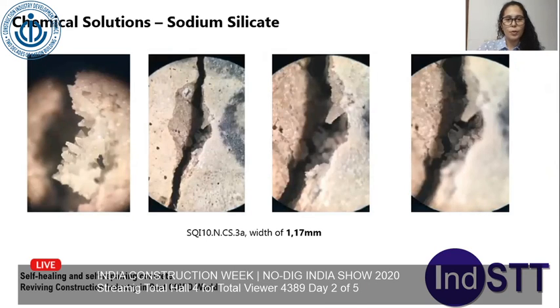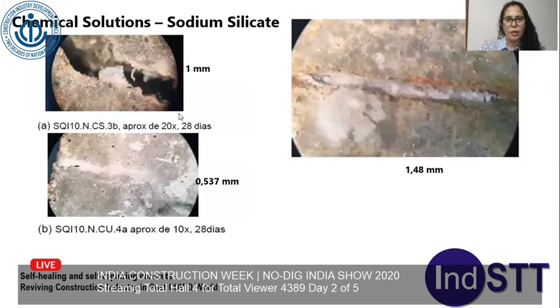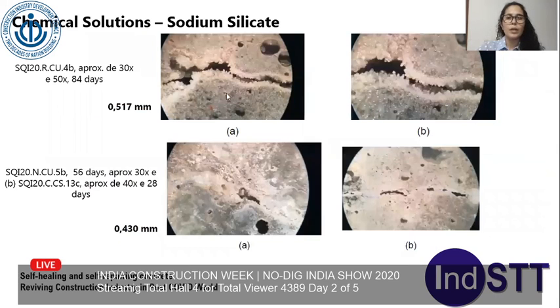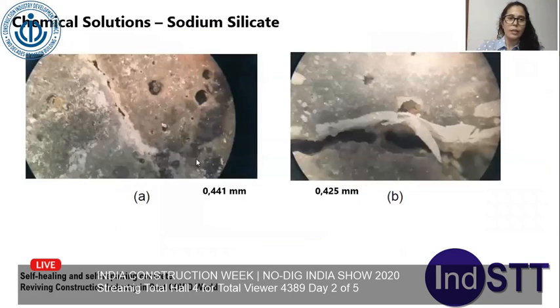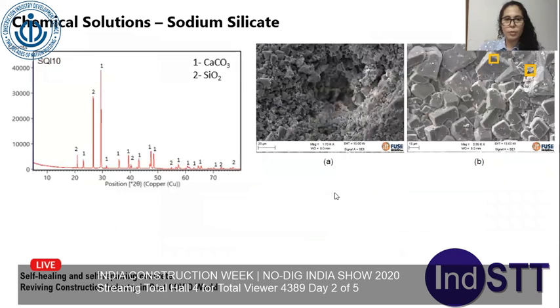Using sodium silicate, we saw the crystal shape, and also we saw a solid material on the crack with 1.48 millimeters, which is really good. And we also have some cracks that were not completely recovered, and here those different shapes of healing with 0.44 and 0.42 millimeters. And also the chemical analysis showing calcium carbonate and silicon oxide, and here the shapes from SEM analysis.